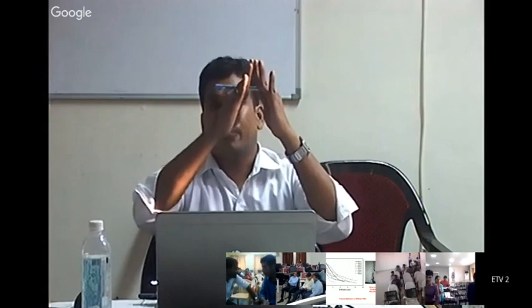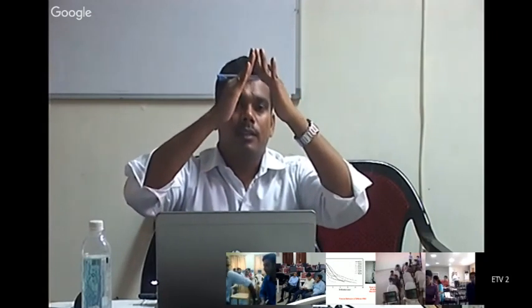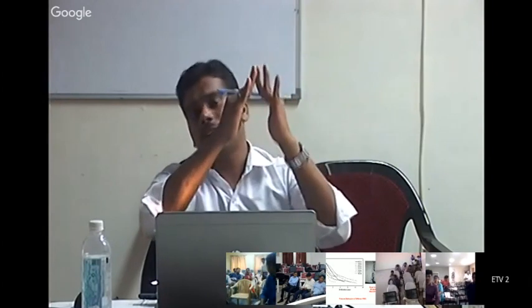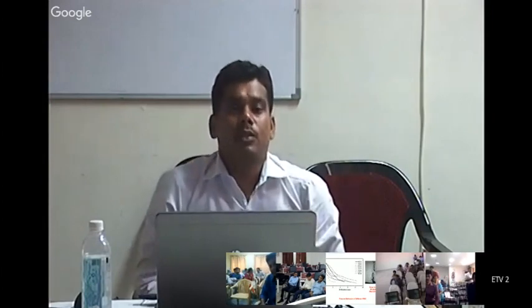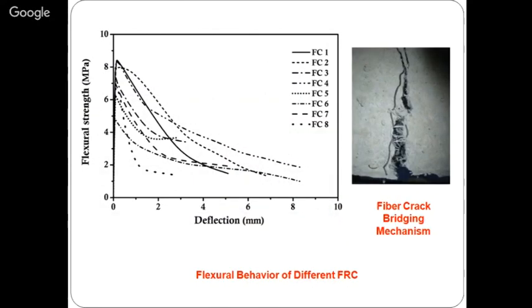So until the entire fiber fails, the crack formation or crack growth will remain very slow. And once the entire fiber fails, then the crack growth will be very, very high. So crack formation is very important in the failure stage. Once the crack is formed in the conventional concrete, there is no method to bridge the cracks, so immediate failure will occur. Whereas in fiber reinforced concrete, the fiber present between the cracks will perfectly bridge the cracks and allow the crack to grow at a very gradual rate as compared with the plain cement concrete. So these are the advantages of fiber reinforced concrete: it will resist crack formation, improve the damage tolerance capacity, add tensile behavior to the concrete, and allow the entire structure to deform to a larger extent, to larger deformation, without going for any critical confinement in the joint region.